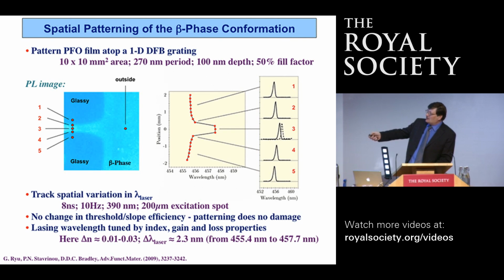What we've actually done is to do this patterning on top of a grating. So underneath this film, there is a grating, and that grating provides a feedback which makes this structure a laser. And then simply by spatially selecting the point at which we excite the laser, we can basically modulate the output wavelength from that laser corresponding to the amount of index contrast that we generate.